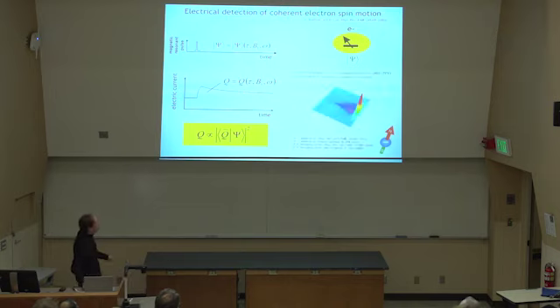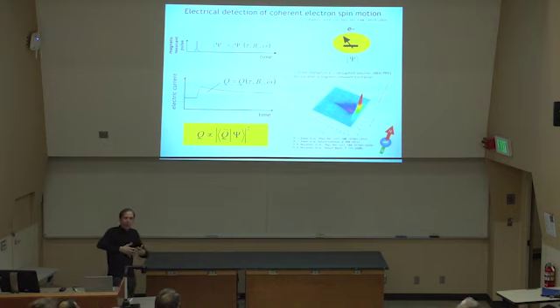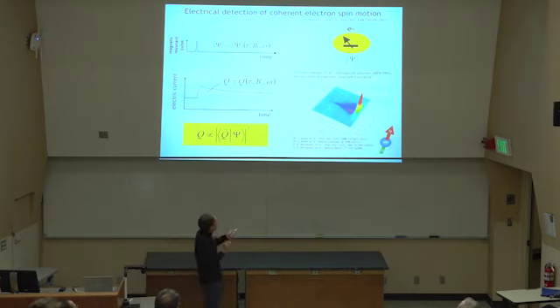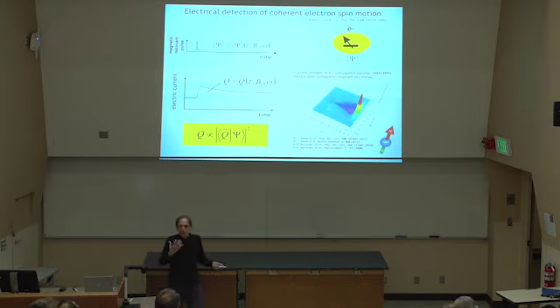We know it works because I showed you the data earlier, except these were just magnetoresistance measurements. So now we look at it on a time scale, and really a long time scale, microseconds, meaning we look here on time scales that correspond to the built-in time constants of semiconductor thin film samples. And so there's a plot of the current change for these thin film devices, similar to what I showed you earlier, actually pretty much the same in size and area.